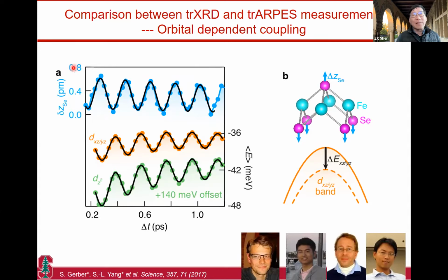This constraint, as you will see later: we know that a typical material has a lattice constant of about a couple of angstroms. So you better not change the lattice constant by 1% or more, because chances are if you change the lattice constant by more, you may well be studying a different material, not the material you intend to study.